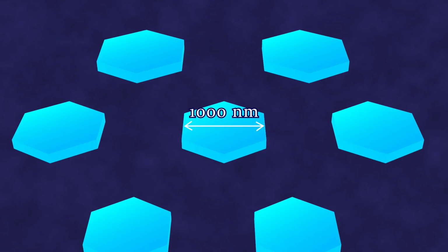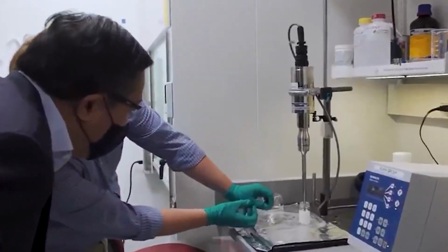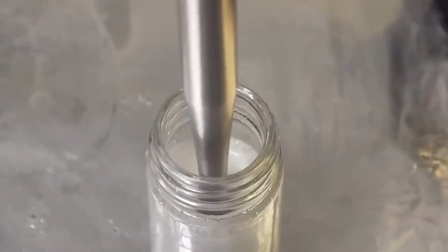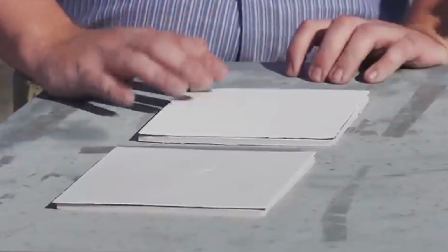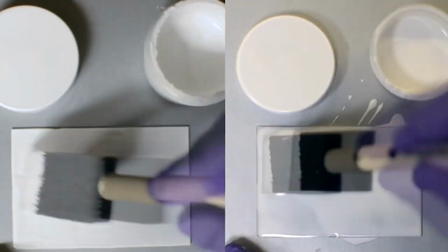The team behind Purdue ultrawhite paint is also working with this technology. In the year 2023, they presented a new version of their coating with added particles of hexagonal boron nitride. This not only increased the effectiveness of passive cooling from 4 to 5 degrees up to 5 to 6 degrees in the daytime version, but also improved the practical properties of the paint. To achieve the effect, it is enough to apply a layer with a thickness of up to 150 micrometers.